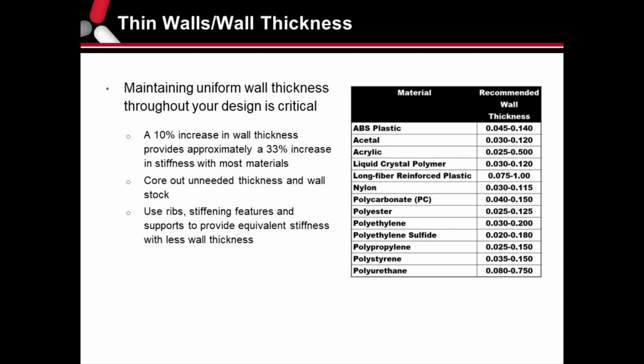Things like that. As John said, as best you can, depending on the application, make sure that your wall thickness is consistent without big sections, thick to thin. That's just going to create some flow issues and so forth that you'd be battling. Yeah, in those thick sections, if you can core them out, introduce ribbing back into the part, and you'll get the same strength, but still have a good looking part. And just some general things here, a 10% increase in wall thickness is going to increase the part stiffness about 33%. And again, as always, good radiuses, try to minimize the sharp corners. That's a thing for all design purposes to really watch out for.